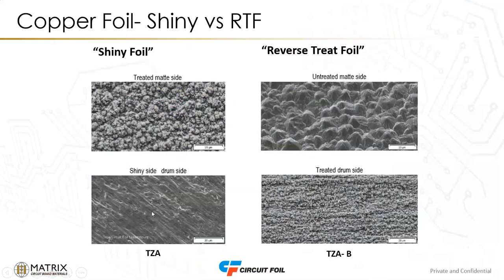On the left-hand side is the shiny foil, and if we're looking at the shiny side, it's called the drum side or shiny side, there's almost no topography at all. The top left-hand corner that I'm pointing at here is the treated matte side, and you can see that has some additional topography that we talked about during that treating process. On the right-hand side is an untreated matte foil. You can see that just has the basic dendrites that were produced during the plating process. And then below that is the treated drum side. So this has additional topography that's plated onto what used to be the shiny side. The importance of that is there's two things. One, this gives the treatment enough to enhance the peel strength, so the laminators can use this, what used to be the shiny side, what still is the drum side, but now it's treated.